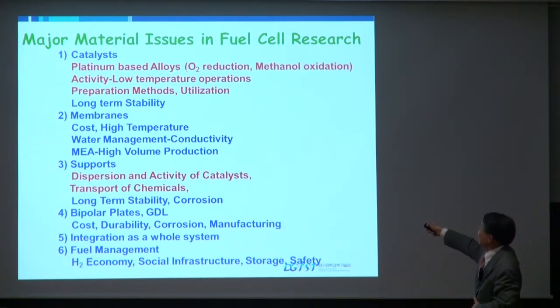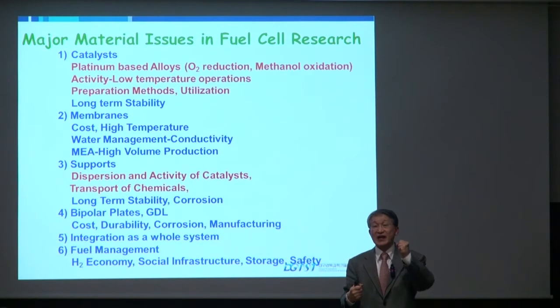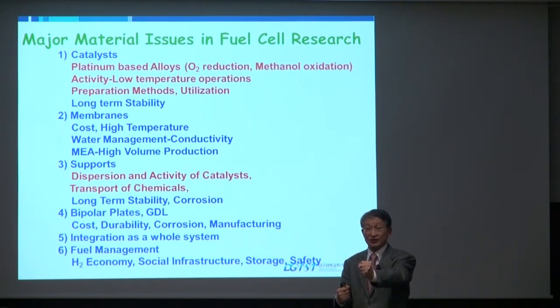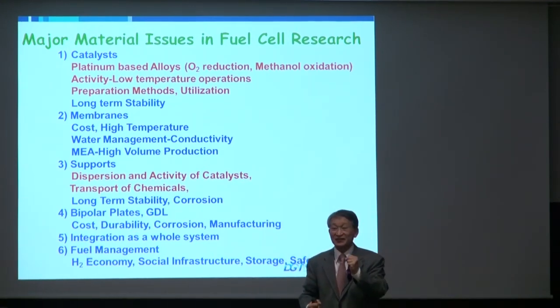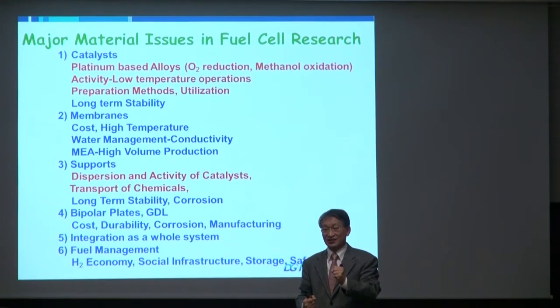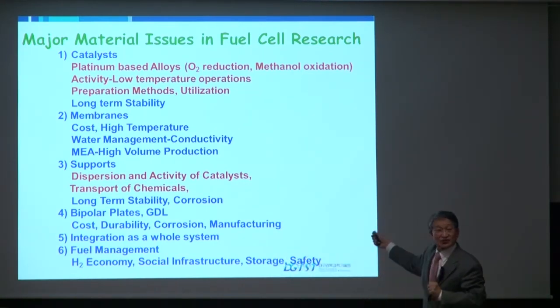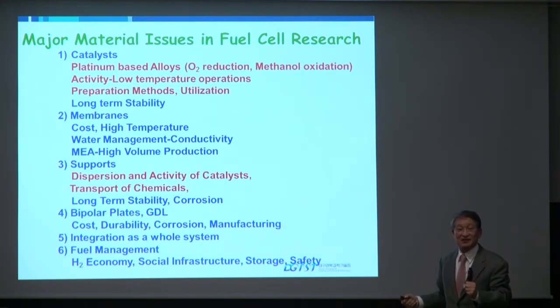Then, oxygen reduction reactions for hydrogen oxygen fuel cells. When you are talking about direct methanol fuel cell, it is oxidizing methanol instead of hydrogen. Still, we are using oxygen. But the oxidation of methanol is even more sluggish than the oxygen reduction reactions. So in DMFC, methanol oxidation catalyst is more important than oxygen reduction catalyst.